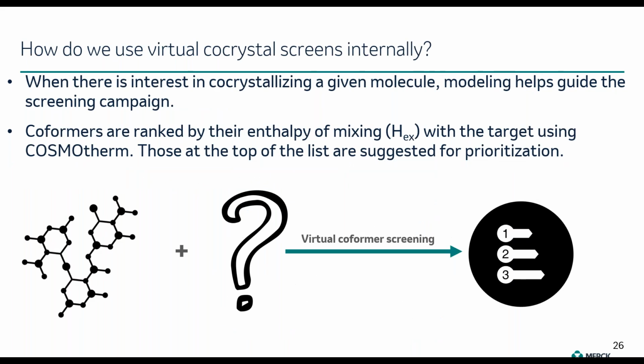How do we use this virtual co-crystal screen within our company? So when there is interest in co-crystallizing a given molecule, we use this modeling technique to guide the screening campaign. We perform virtual screening. We rank the coformers of a given molecule that we want to co-crystallize by the enthalpy of mixing using Cosmotherm. And then we suggest for prioritization those at the top of the list.